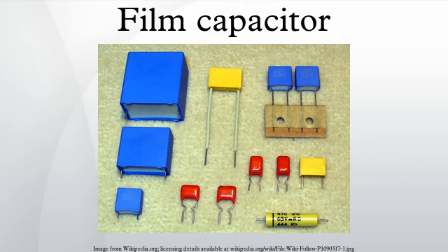To avoid breakdowns caused by weak spots in the dielectric, the insulating film chosen is always thicker than theoretically required by the specific breakdown voltage of the material. Films of less than 4 micrometers generally are not used for film foil capacitors because of their excessively high numbers of point defects. Also, the metallic foils only can be produced down to about 25 micrometers in thickness. These trade-offs make the film foil capacitor the most robust but also the most expensive method for increasing surge current handling.